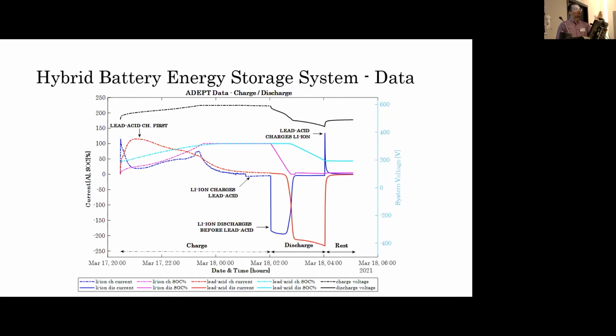Once you start charging and you stop at that point, you see some fluctuations between the strings because of the different time constants. So, for example, from this point to this point, the lead acid string is charging. Now, from this point, we're starting to discharge. This is the fundamental point of this presentation. When you start discharging this system, the first thing that discharges is lithium-ion, which is counterintuitive. If you have two batteries connected together, like in high school, and you discharge with 10 amps, you expect one string to give 5 and the other 5 amps. Equal sharing. That's not what happens.